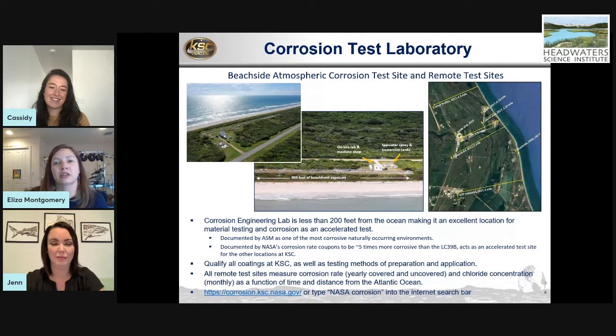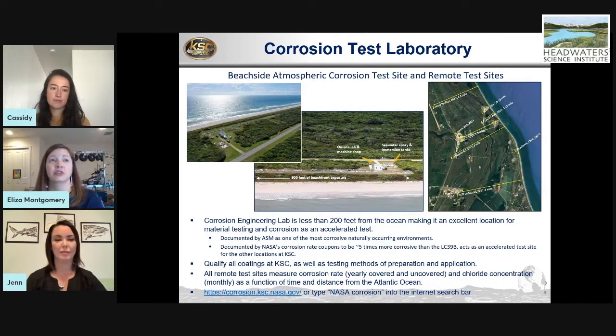We're located here at the beach site, but we have all these little sites here that are all different corrosion sites. We measure corrosion rate and chlorides as a function of time and distance from the ocean every month. So we understand how much more corrosive it is at our site versus at the launch pad. The reason I do that is because I can use my test site as an accelerated site. I can test something for 5 years at my site and know that it will last 20 years at my launch pad because we're accelerated.